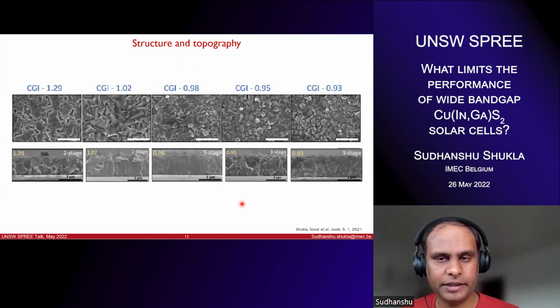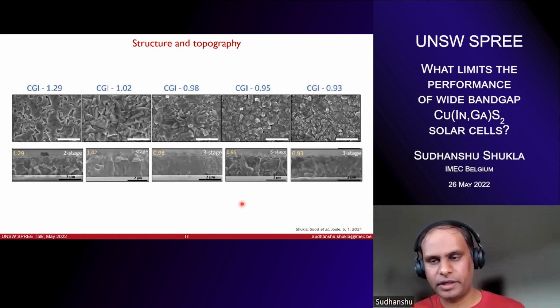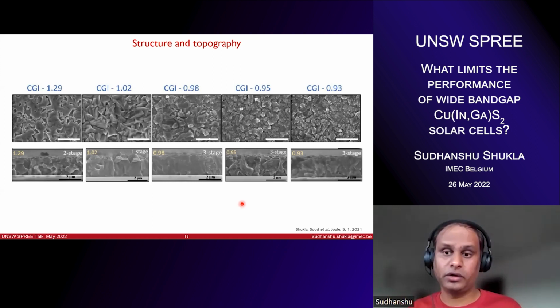Actually, I want to highlight here that when you do a 3-stage evaporation, the way we control the final stoichiometry is by playing with the duration. So when we do a longer duration third run, we get a copper-poor absorber. Remember, you also have longer annealing times, because when you do a longer run, you are effectively annealing the absorbers for a longer time. That can actually contribute to the grain growth. We don't know. We are actually studying that from cathodoluminescence recently.